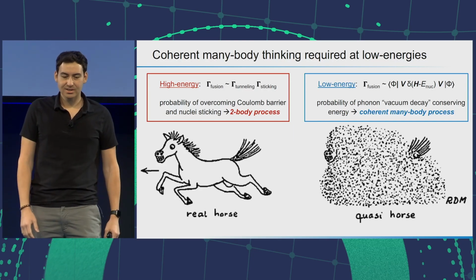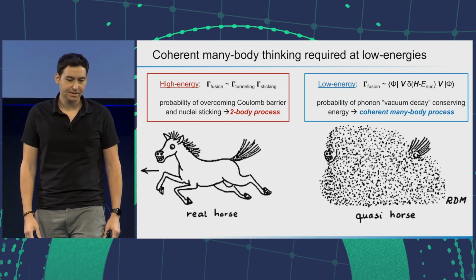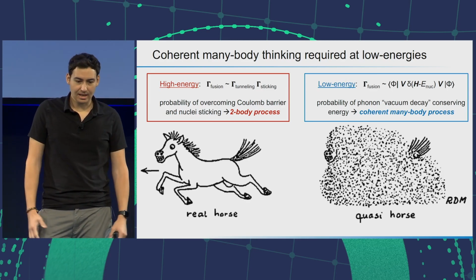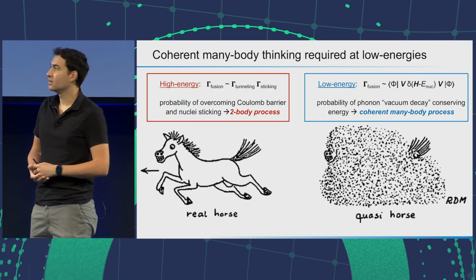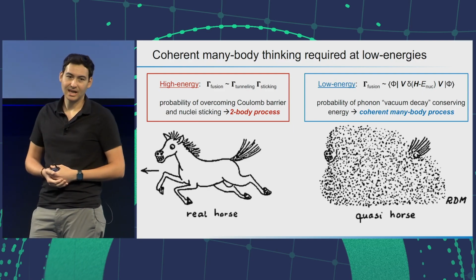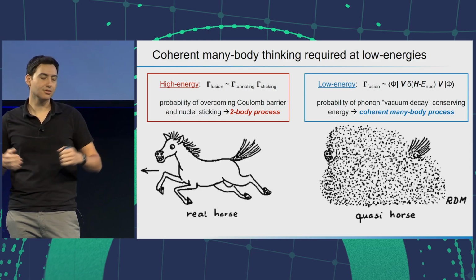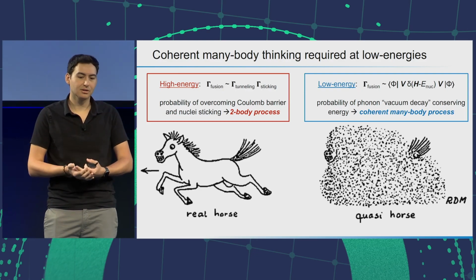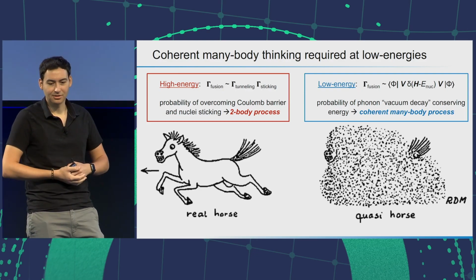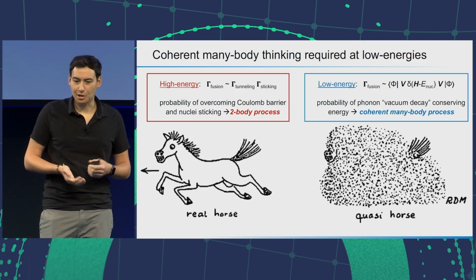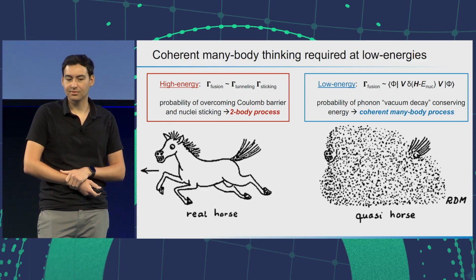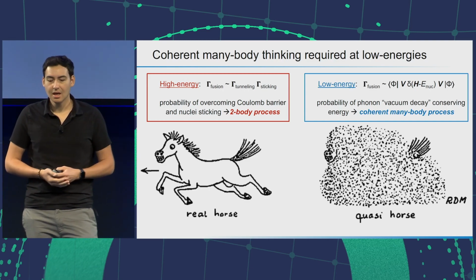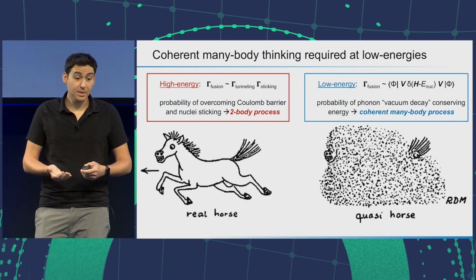But at low energy scales, the problem becomes more interesting and more complex. The lattice degrees of freedom can play a role, and so he studied the fusion rate in terms of a vacuum decay. So starting with a system of, imagine, 0 phonons, you have a decay, a nuclear event that transfers energy and creates a large number of phonons. And so this requires a large number of phonons because they are low energy degrees of freedom. It's a coherent many-body process, but it's the type of thinking that at least got me interested in the field